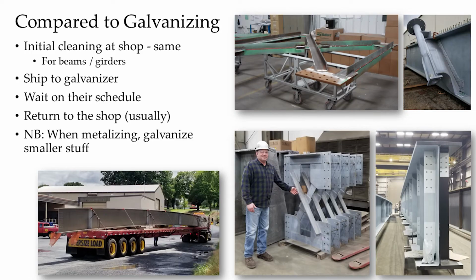You can do it, and we do, but compare that to dropping that anchor assembly into a kettle, right? The galvanizing will cover everything readily and completely. You look up inside that corner, certainly an important component of the assembly, a possible area where water could accumulate maybe and give you a durability problem. You certainly want to make sure you have a good coating there. In my opinion, our opinion, you just really don't want to try to metallize something like that when you can galvanize it so readily.